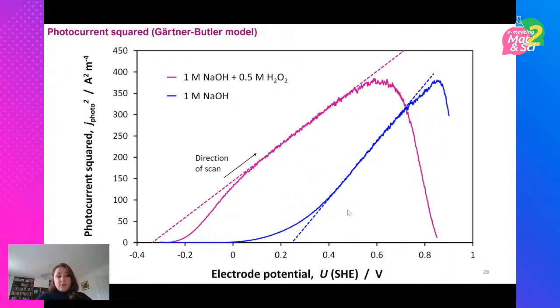When we do the photocurrent squared, it's obvious that recombination actually plays a very big role in the data that you can see. So if you don't have some sort of charge scavenger, recombination causes a very positive onset in the photocurrent, which is obviously the problem with a lot of semiconducting photoelectrodes. There's too much recombination, cannot beat it, and so the photocurrent flows at very high potentials, which start to negate the benefit of having a photoelectrode in the first place.